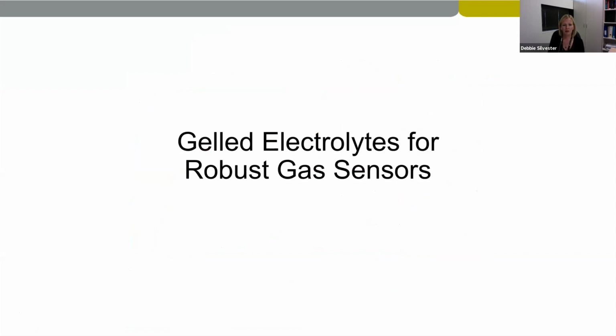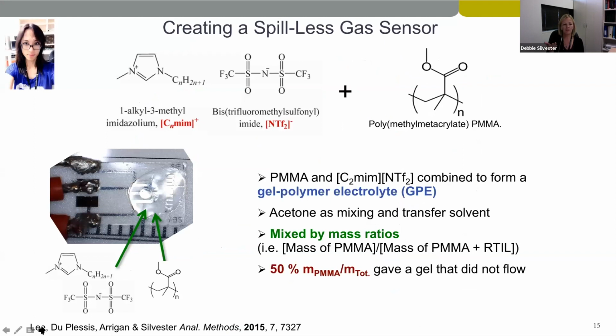The second part of my talk will be focused on making more robust sensors. And so we've just talked about using liquids so far. And one of the issues with a liquid is that we can have spillage of the liquid over the planar electrode. So my postdoc Jenny combined a typical ionic liquid, a C2-MIM NTF2, with polymethyl methacrylate, and this has been shown in the literature to form very nice homogeneous films.